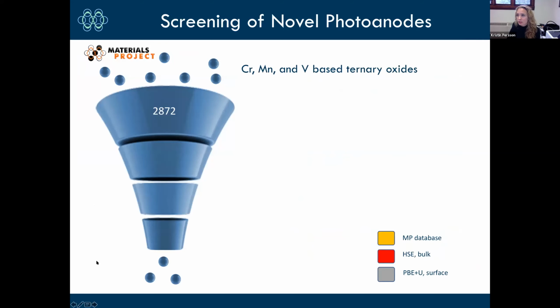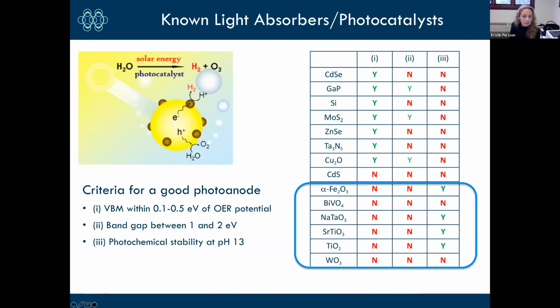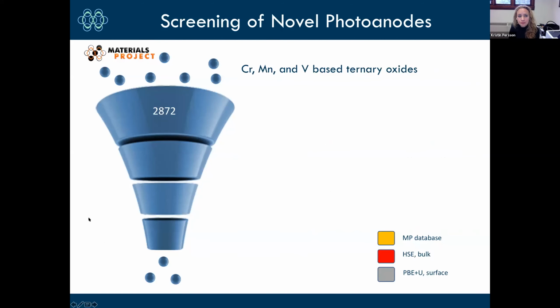And so we decided not to go after the whole project, all of its data, but focus on chromium, manganese, and vanadium-based ternary oxides. This was in discussion with our experimental colleagues who thought that this was a promising space to go after. If you just filtered in those days on oxides that contain chromium, manganese, and vanadium in the Materials Project, you get about 3,000. And this is a search you can do that will take you 5 minutes with our API. So no calculations have been made yet.